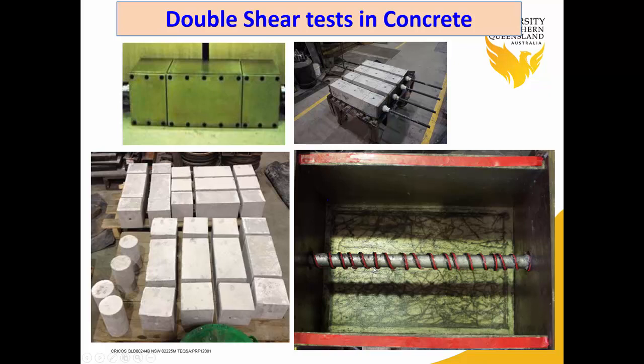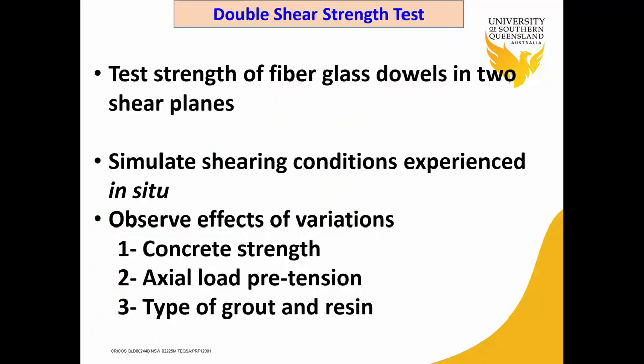In order to produce the rifling, the rod that is positioned inside when the concrete is cast is wrapped with a wire to provide the imprint of the rifling. So once the sample is made, the rifling as we have it in the field can be seen in the sample. The double shear test is carried out to simulate shearing conditions as experienced in situ. The intention is to observe the effect of concrete or strata strength on the strength property of fiberglass rockbolts, to investigate the effect of axial load or pretension value on shear strength, and how the type of grout and resin can affect the shear strength of fiberglass rockbolts.